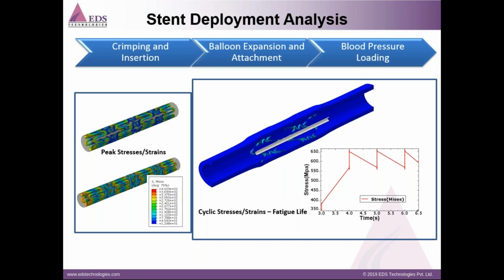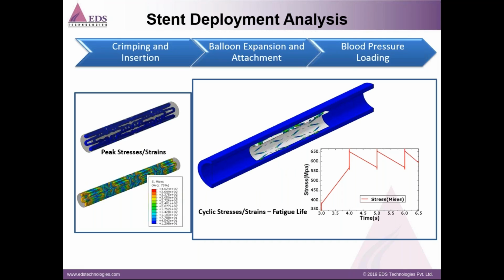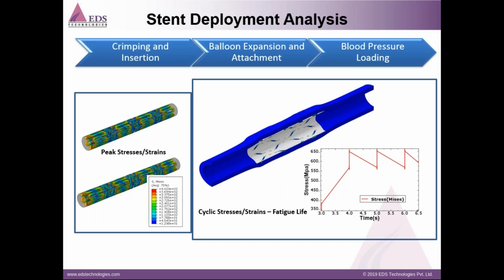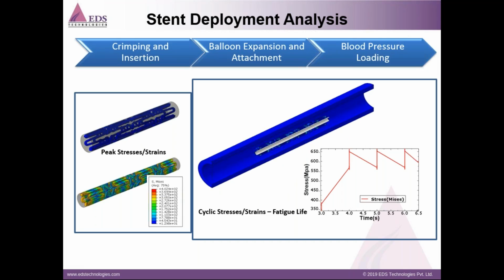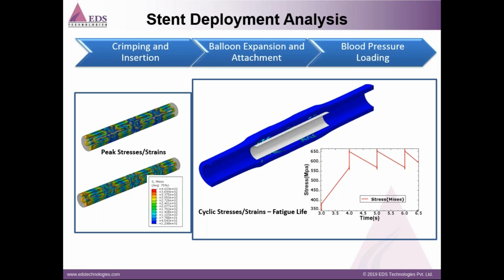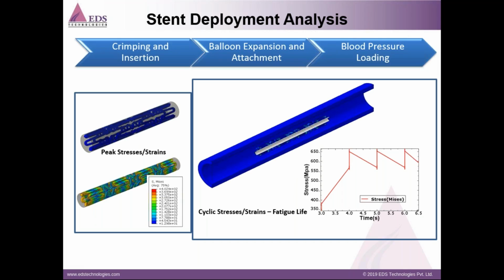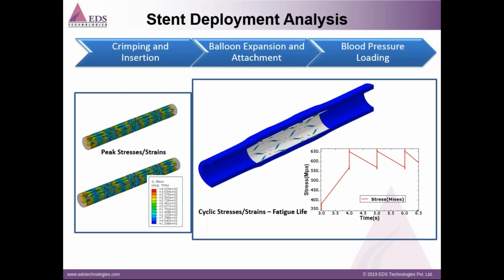This also leads to the stress shown in this graph as the maximum stress in the stent, and as you can see, as pressure increases and decreases, stress also goes through the same cyclical pattern. Because of this cyclical pattern, where stress and strain undergo this cyclic pattern, the fatigue life of the stent can also be estimated.